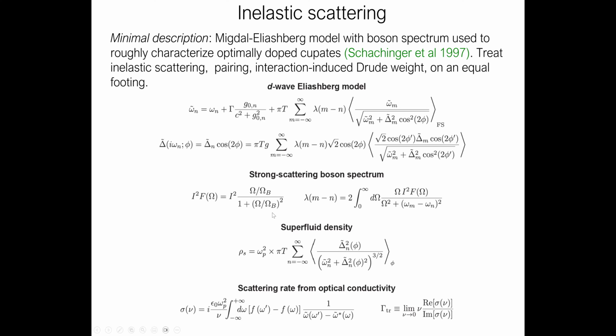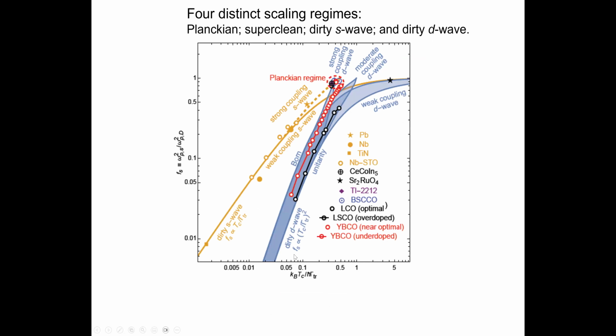This could be an Einstein phonon. It could be a spin fluctuation, a very sharp one, anything. We plug it into the superfluid density, get the scattering rate from the optical conductivity, and we replot this, including the inelastic scattering, for three different assumptions about the inelastic scattering: weak coupling, moderate coupling, and strong coupling. And that just relates to how high the boson frequency assumed is compared to the size of the gap in the system.